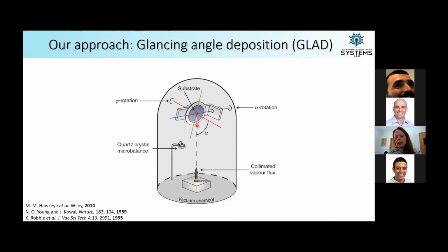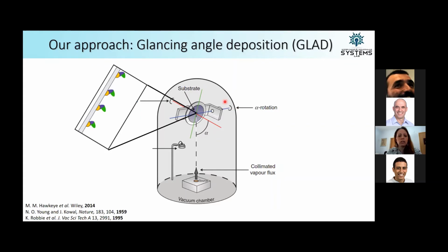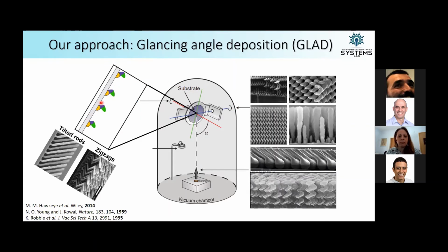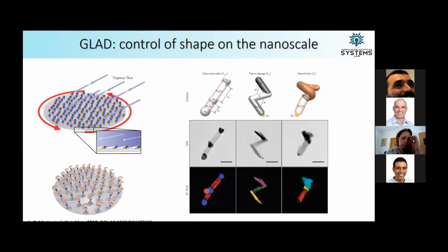This angle allows for what is called shadow growth. So you end up with different kinds of grains, and these grains shadow the incoming vapor flux, and then they end up forming varieties of rods and nano shapes, so zigzags, helices, and all these different things that you can see over here. And in our lab, we've actually been able to obtain several types of shapes, single shapes on one substrate. So we deposit only one type of nano shape, for example, these nano hooks, nano zigzags, and nano barcodes, which each were deposited separately on individual wafers.